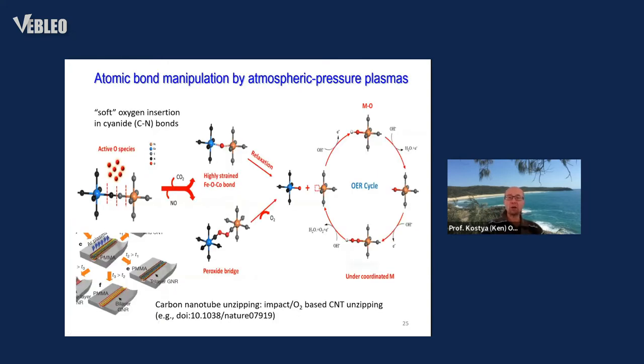The mechanism that we revealed behind this transformation is related to the interaction of plasma-generated oxygen species, that are generated directly in air, when they interact with the PBA network and the cyanide bridge connecting cobalt and iron atoms. So when this bridge is ionized, the bond is broken and atoms rearrange. So it affects the oxidation states of both metal atoms, and it forms a peroxide bridge, and it affects the performance of this catalyst in the oxygen evolution reaction. And as it turned out, very positively.